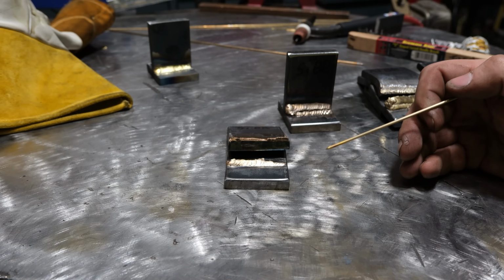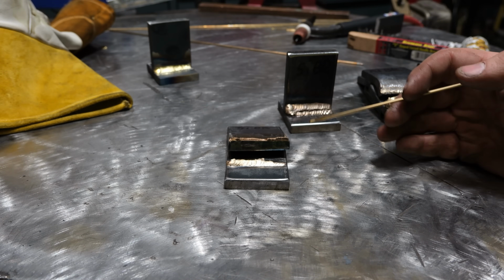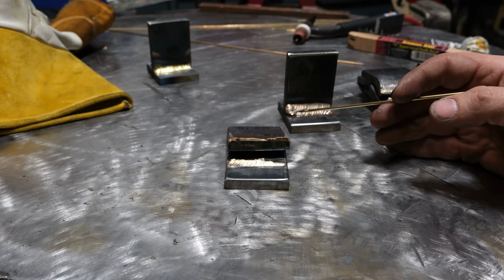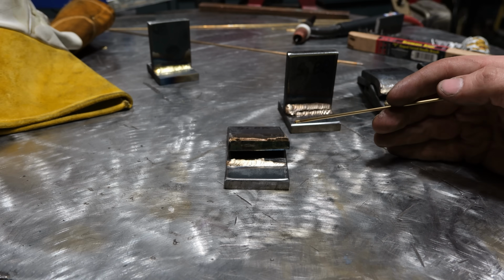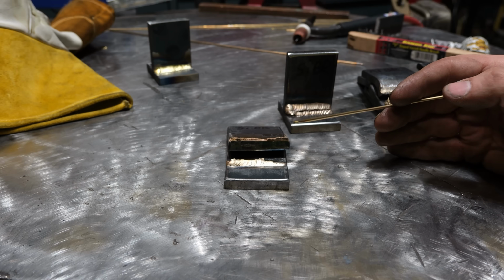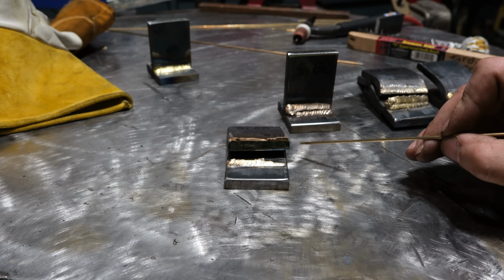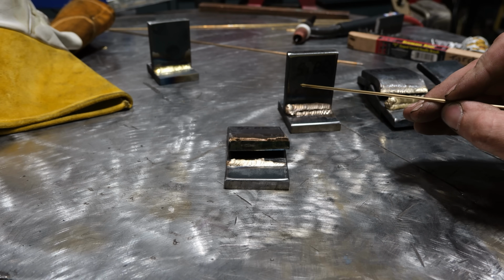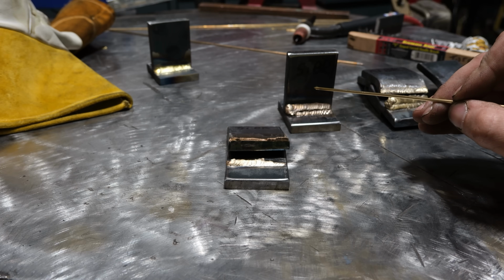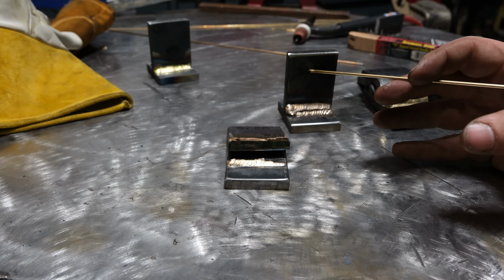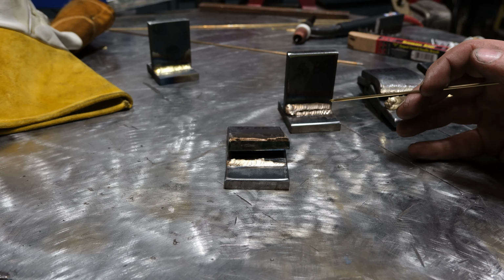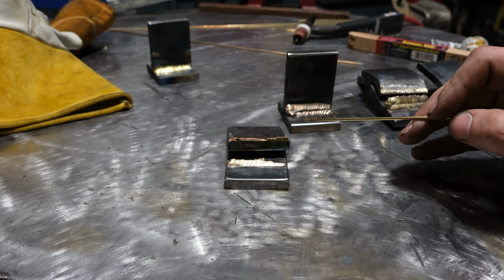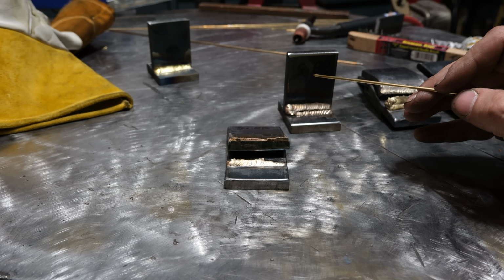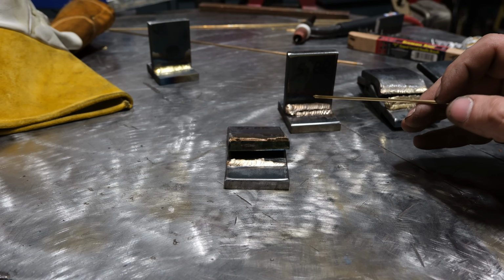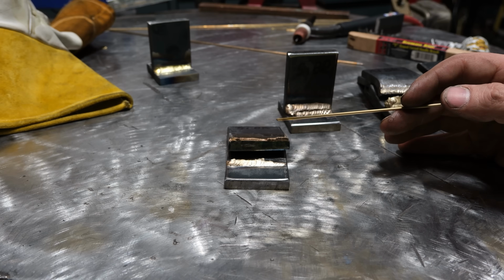Well, we have some catastrophic failures, and that's to be expected. When you're dealing with stuff like this, it's not like normal metal or a weld where you put the pressure on it and it climbs, and climbs, and then you'll see a reduction in pressure or strength, like it's starting to give a little bit, and then it fails. This stuff pretty much will hit a pressure and you don't see that and it immediately fails. And again, to be expected.